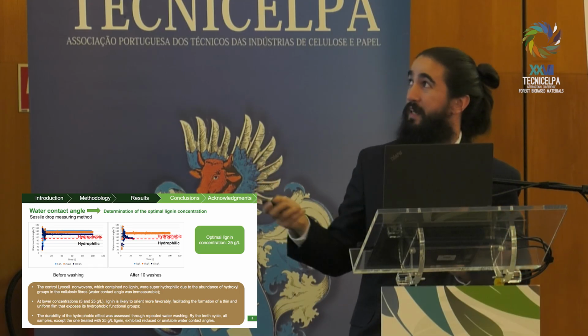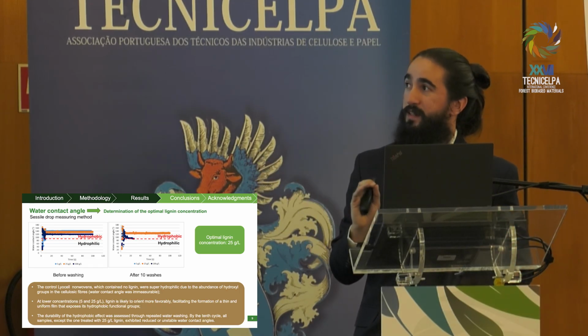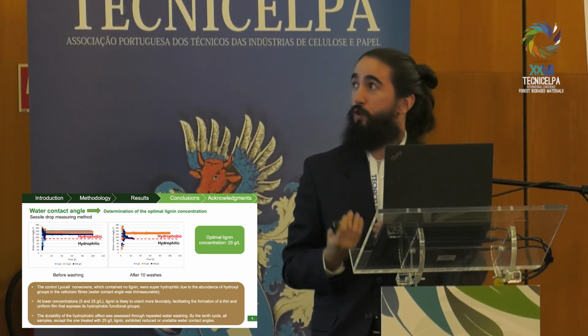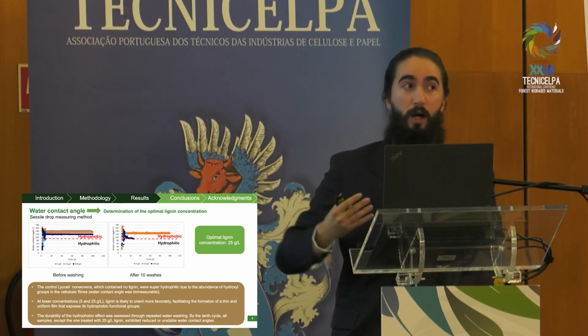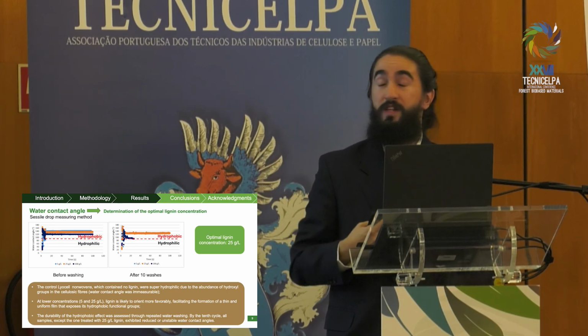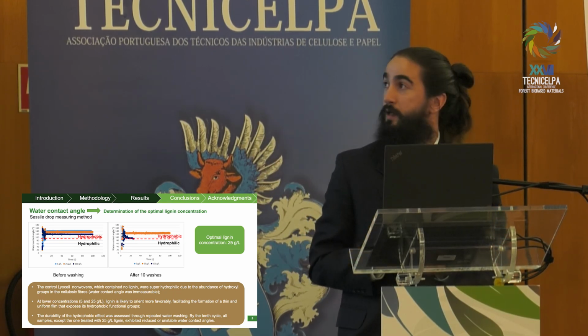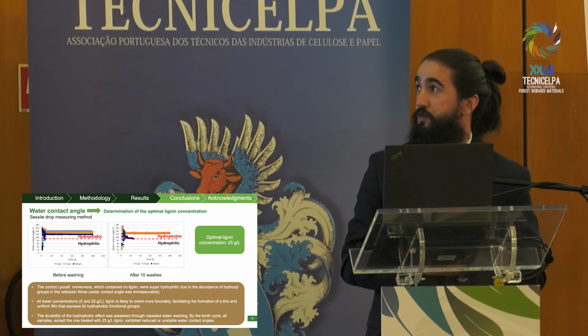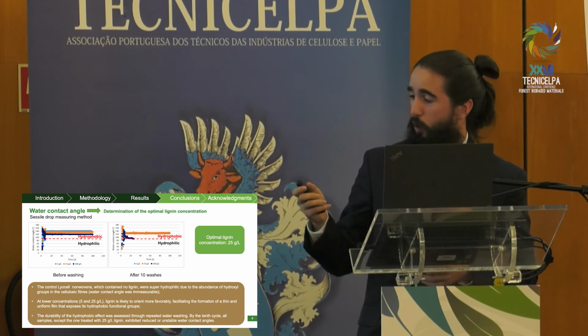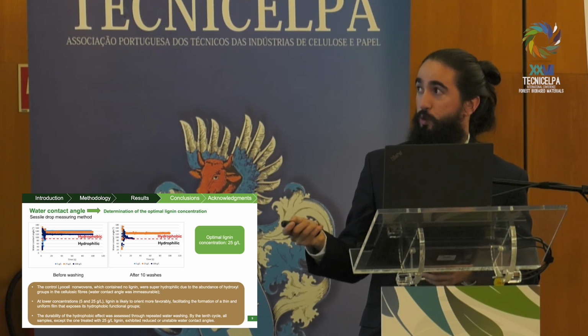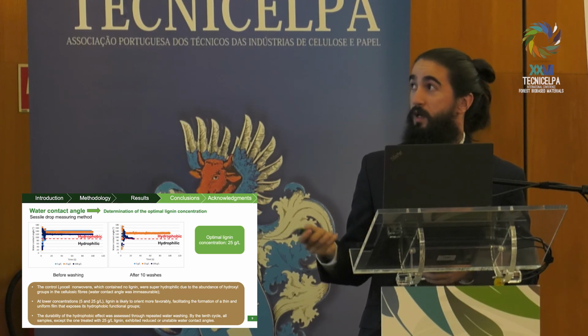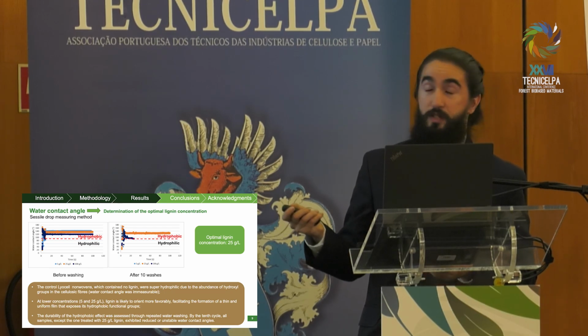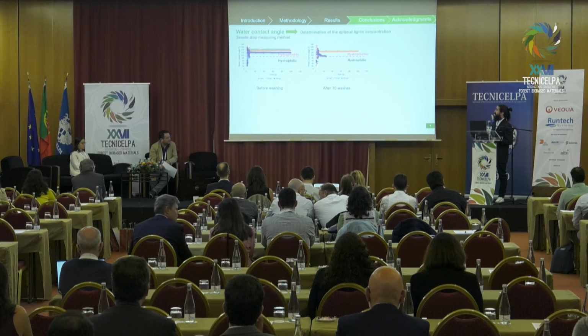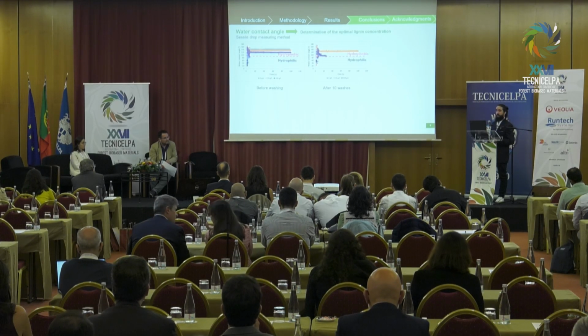In this next slide, we want to set how much lignin we need, because if we want to translate this into an industrial process, we want to have an efficient process. We don't want to waste any money on unnecessary resources. So what we did, we assessed the contact angle with 5, 25, and 100 grams per liter. You can see clearly that it's hydrophobic and it's very stable. But after 10 successive washes, only the intermediate concentration worked, which is interesting.